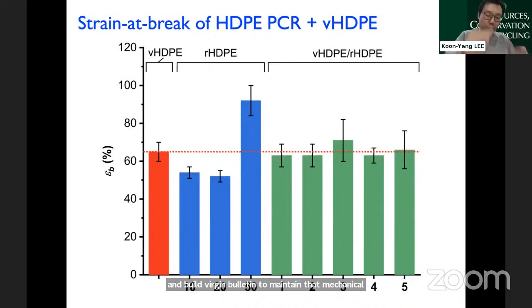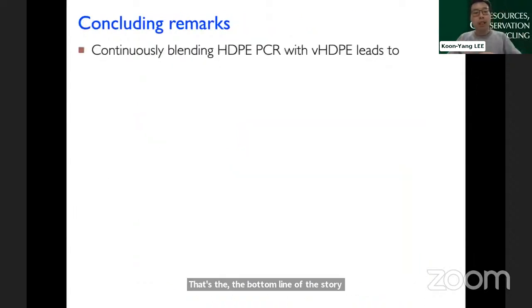So using purely recycled polyethylene doesn't really help. You cannot recycle polyethylene indefinitely without putting in virgin polyethylene. That's the bottom line of the story here. To quickly sum up, we can continuously blend post-consumer high density polyethylene with virgin polyethylene, but just be aware that your color will change. Just be aware that you will have degradation products retained within the system if you continuously blend them without removing them.